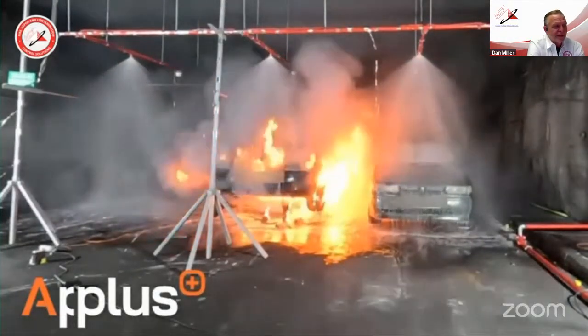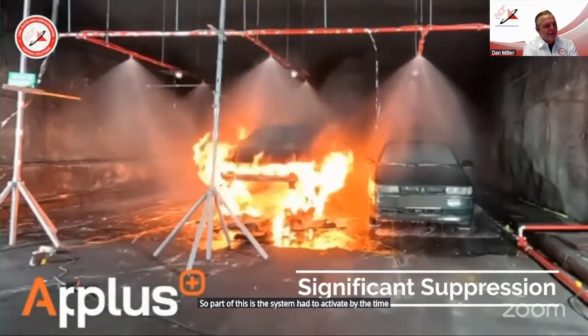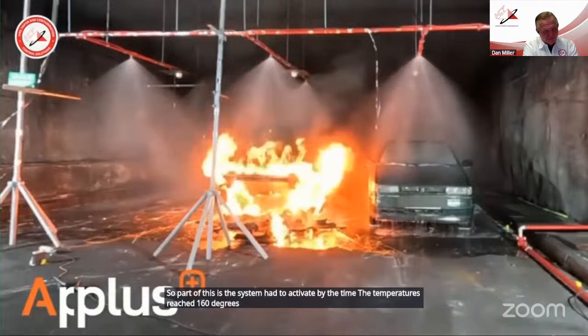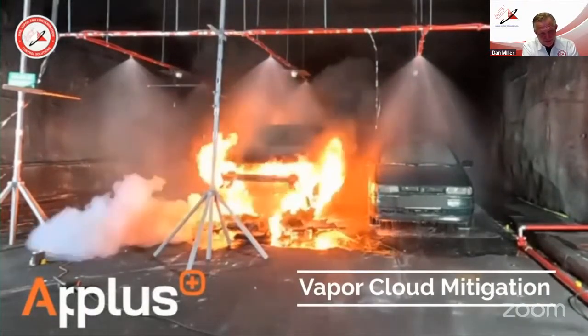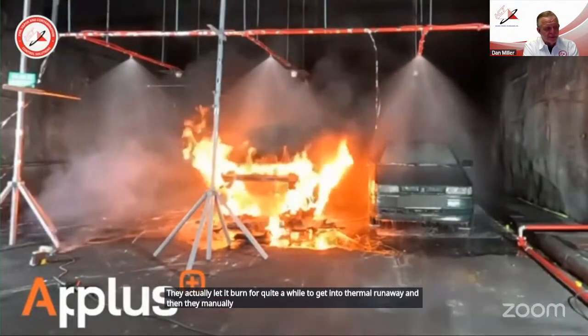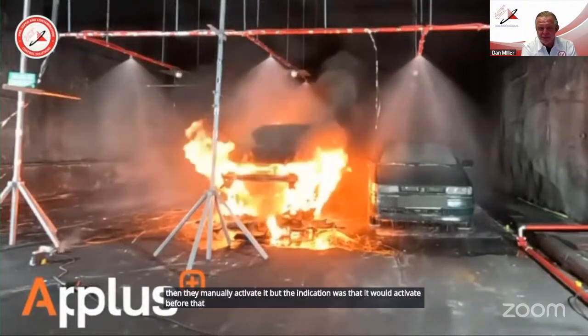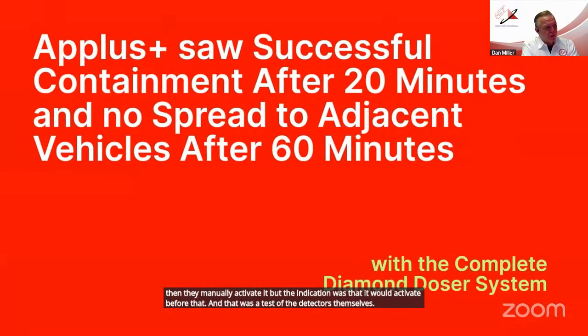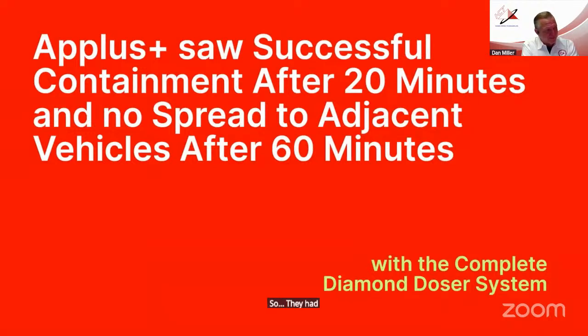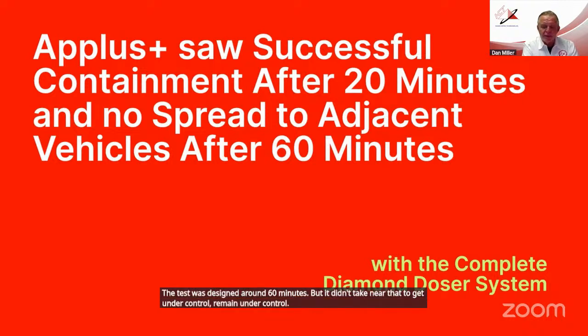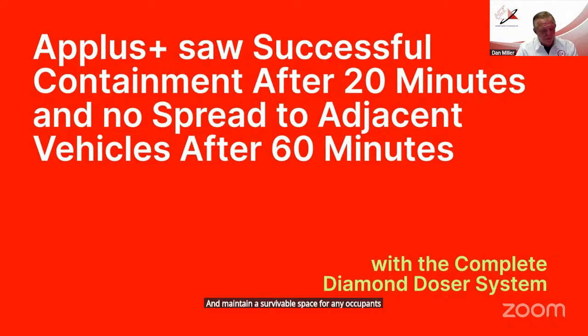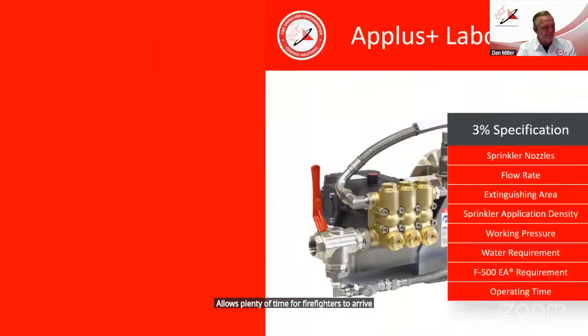So part of this is the system had to activate by the time the temperatures reached 160 degrees Celsius at the ceiling. They actually let it burn for quite a while to get into thermal runaway, and then they manually activated it. But the indication was that it would activate before that. And that was a test of the detectors themselves. So they had 100% containment after 20 minutes and no spread to adjacent vehicles after 60 minutes. The test was designed around 60 minutes, but it didn't take near that long to get under control, remain under control, and maintain a survivable space for any occupants that might have been in that space. Allows plenty of time for firefighters to arrive and remain in control.